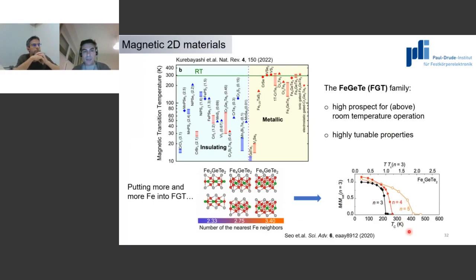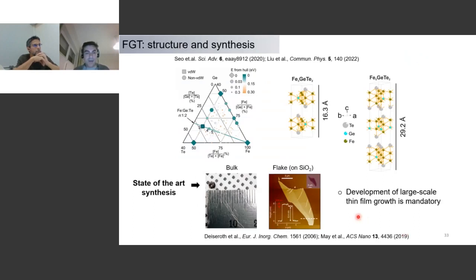Of course, this is important to be able to have a Curie temperature around 300 Kelvin or even higher, because if you want to produce a device, you want to have that working ideally at room temperature, and not only at low temperatures. Anyway, I will skip this part here, but it essentially shows that it's theoretically predicted that these different phases are indeed stable in the 2D and the van der Waals phase.